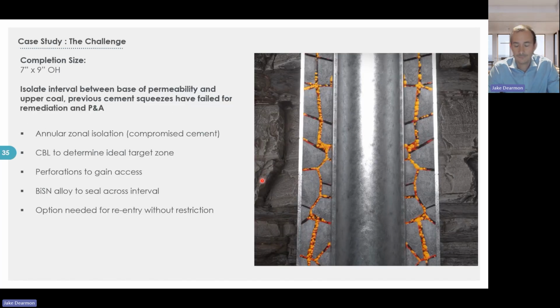So in this particular case, it was a 7-inch completion by 8.5 or 9-inch open hole. We needed annular zonal isolation, so we wanted to create that annular isolation of gas percolating up through compromised cement. To begin that, we look at a CBL to determine the ideal target zone. So what is the likely formation it's coming from? What kind of cement do we want to set in? Depending on the application, sometimes we want to set in a well-cemented situation. Sometimes we want to set on top of cement if there's a top, like in free pipe, but we use CBL to analyze a lot of those wells.